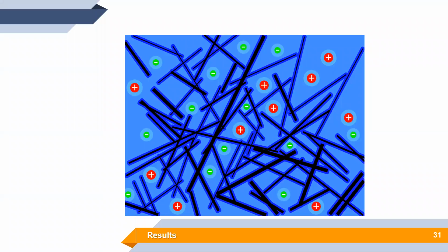Even in this simplest scenario, use of the two-fraction fast exchange model would lead us to over-parameterization of the model. Of course, we are able to get a good mathematical fit to experimental data, but we are able to get equally good fits for different sets of parameters. Because of this, the results are unfortunately not very reliable. So we also exclude this approach.